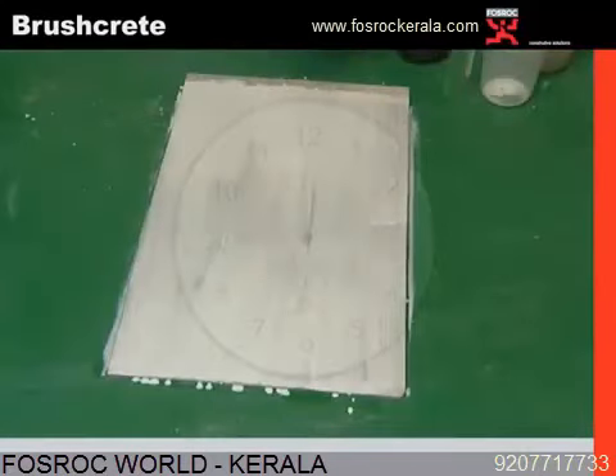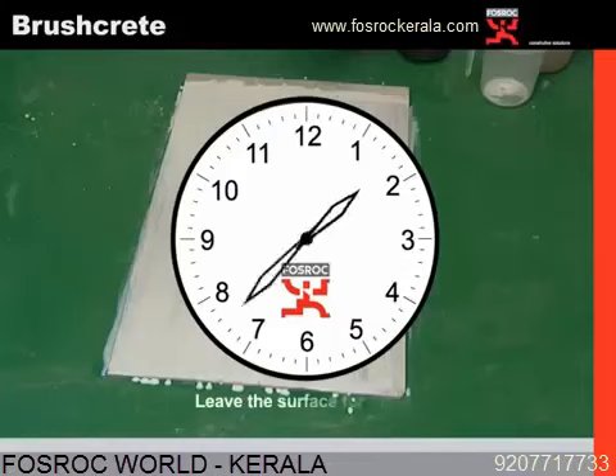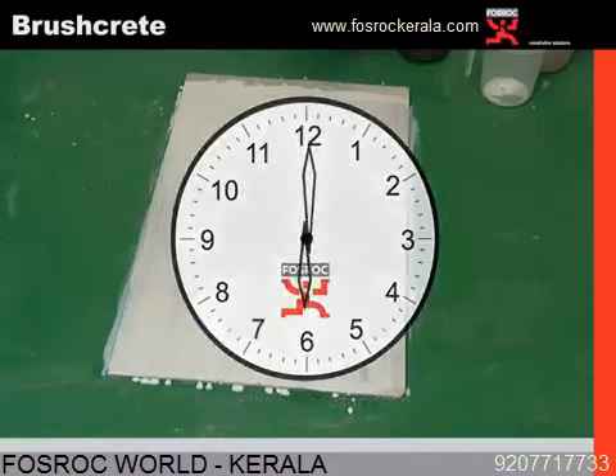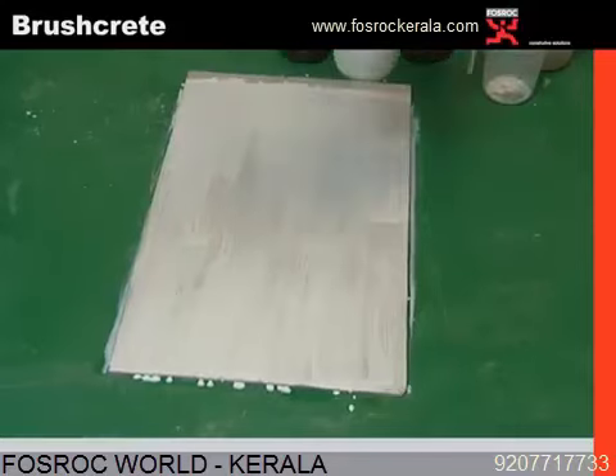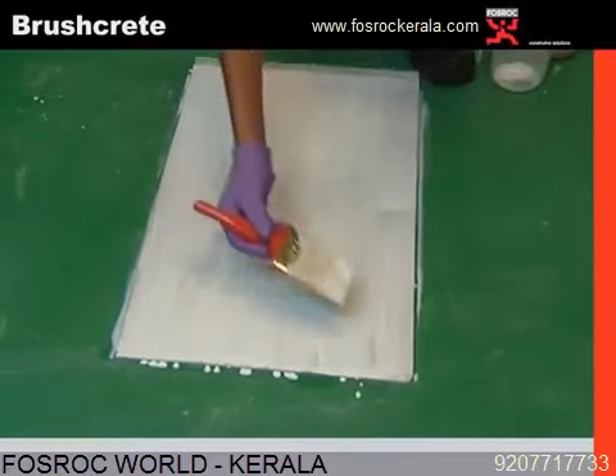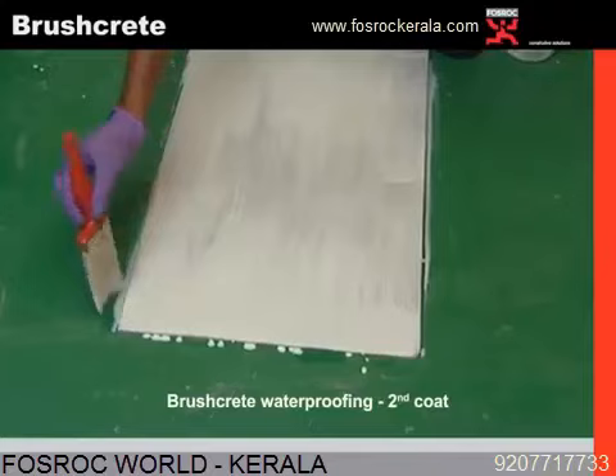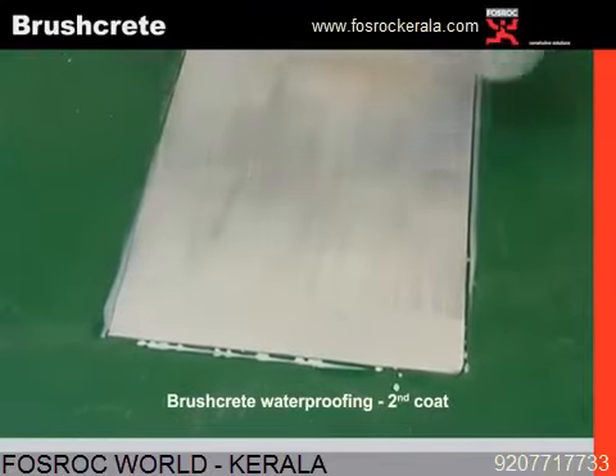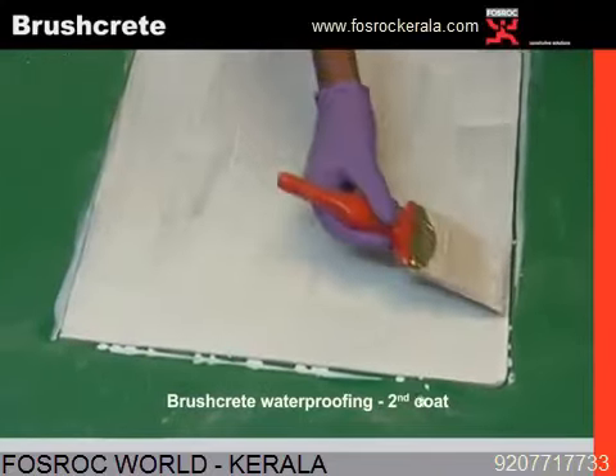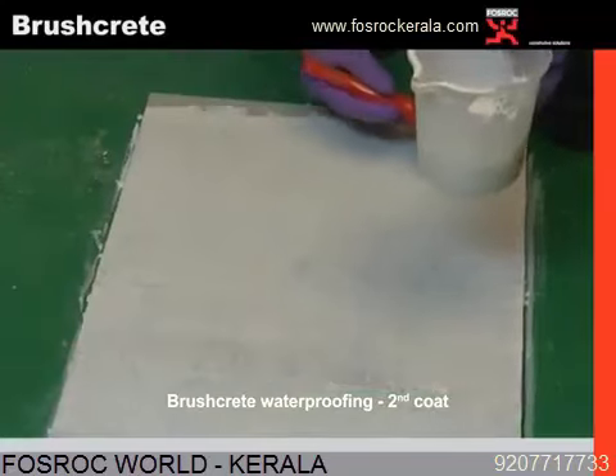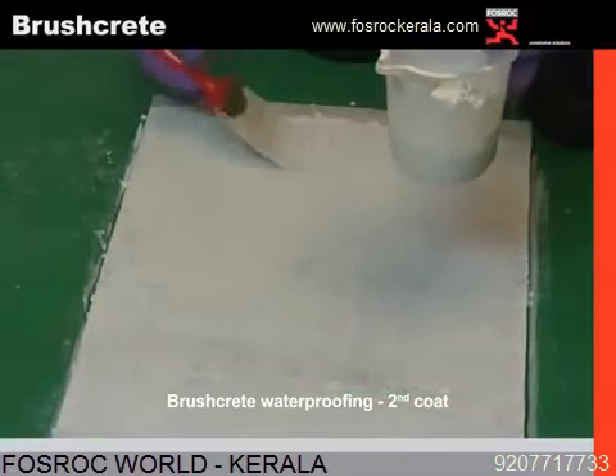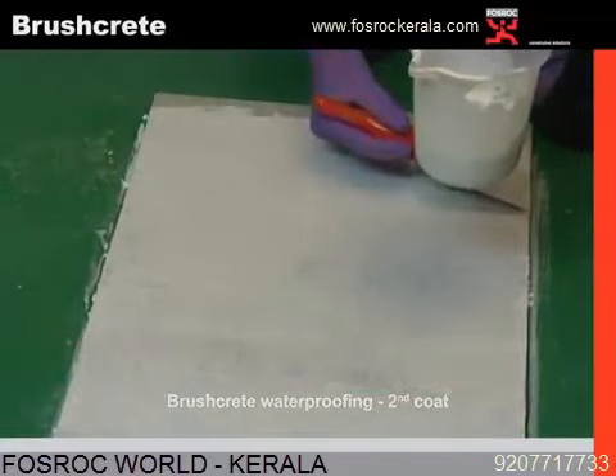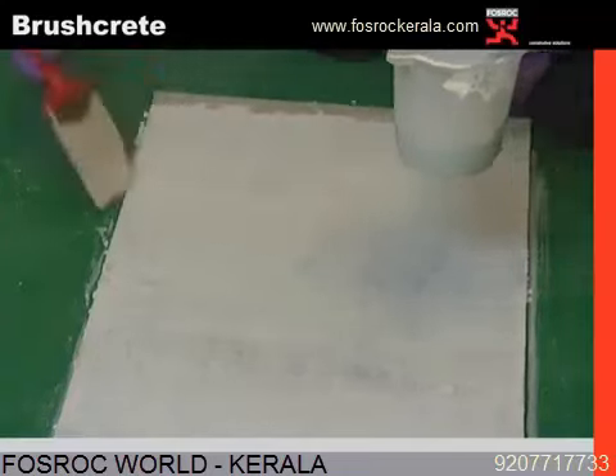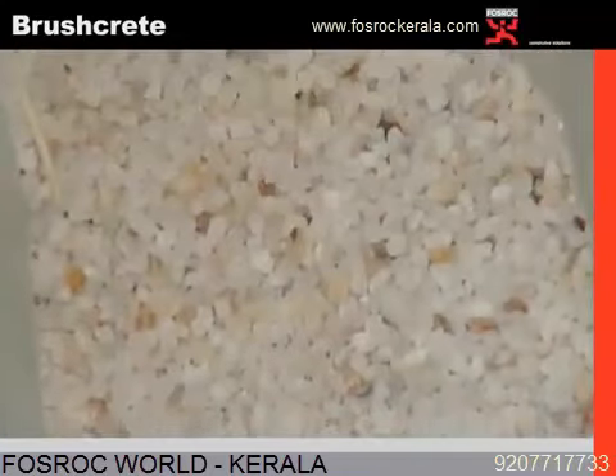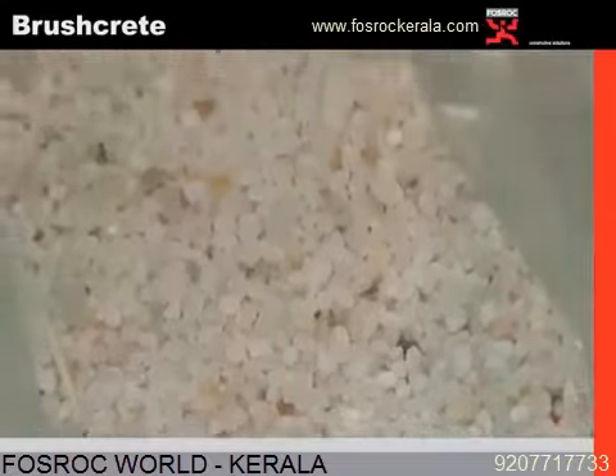Once the first coat is applied, we need to leave it for curing for a minimum of 6 hours or till the coating is dried. Then the second coat is applied in exactly 90 degrees or perpendicular direction as shown. This change in direction becomes mandatory for making the waterproof coating convert into a mesh, which results in the best waterproofing properties. Immediately after the second coat, the silica sand or normal sand is sprinkled as shown.